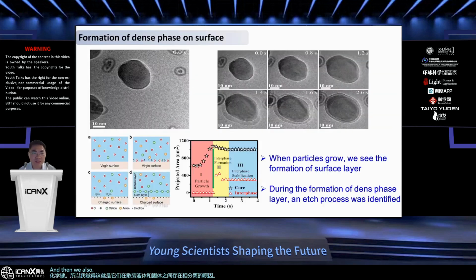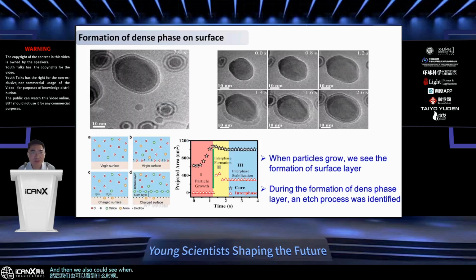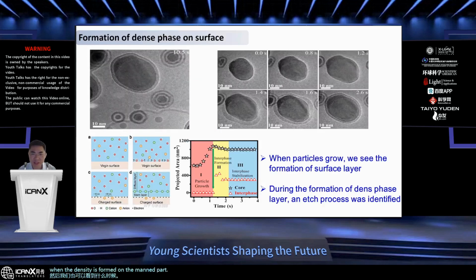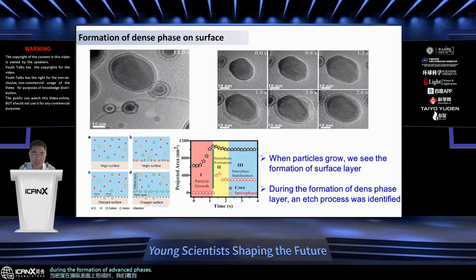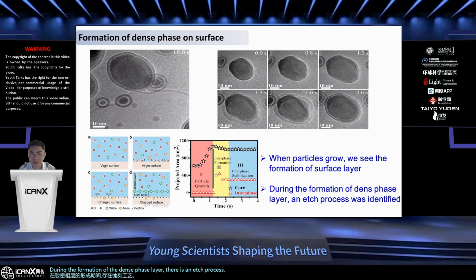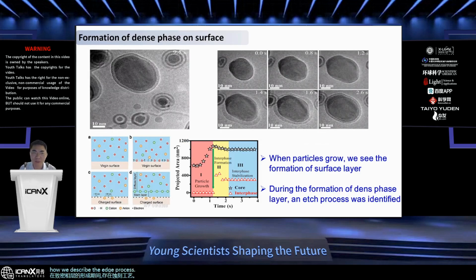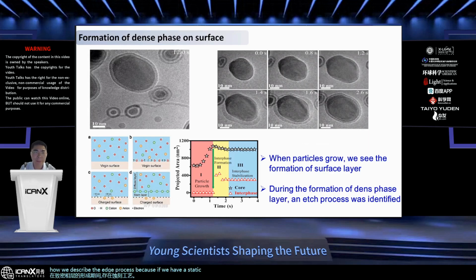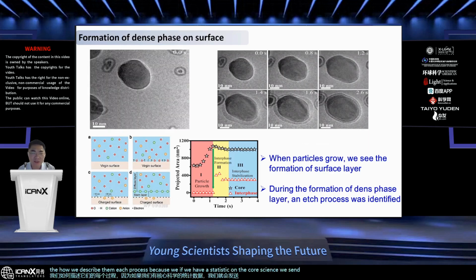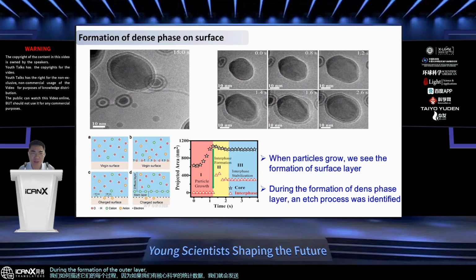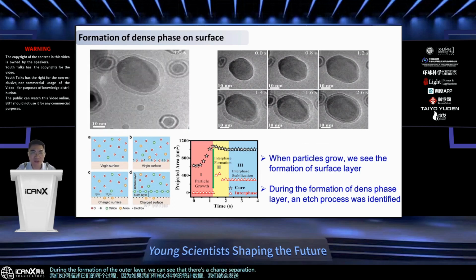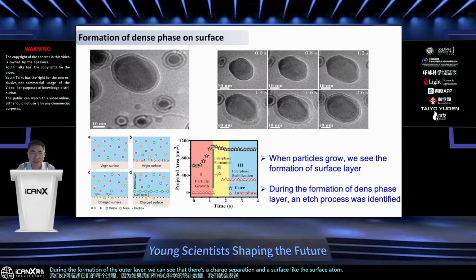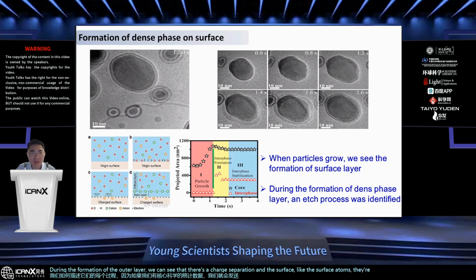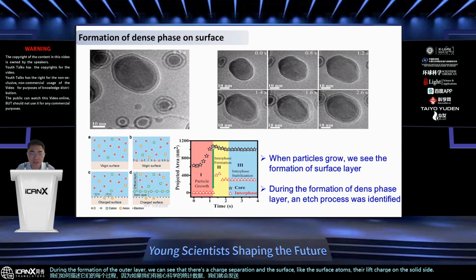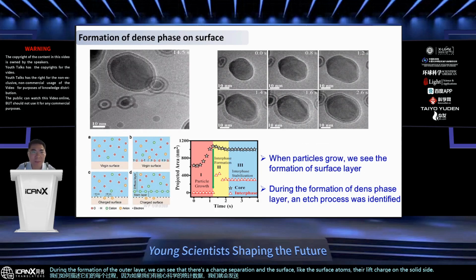And we could also see that during the formation of the dense phase layer on the nanoparticle surface, there's an etching process. How do we describe it? If we have statistics of the core size, we can see that during the formation of the outer layer there's a charge separation. The surface atoms leave charge on the solid side, and these ions go to the solution side and form this kind of dense phase.